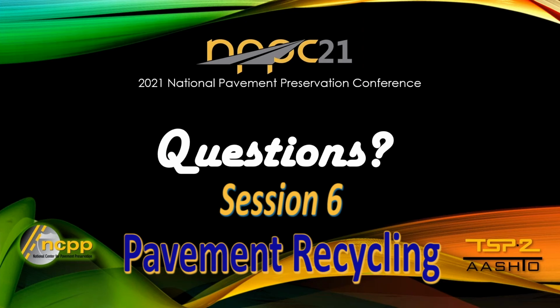It's heavy with binder. You've got some aggregate in there that you can reuse. And if it's an old, worn out chip seal, as typically we see on some of our urban highways that we're recycling, it does just fine. You can get in some problems if you've got 2 or 3 vintages of chip seals on top of the roadway you're trying to recycle. So we have milled that off before starting the recycling process, but if it's manageable and not a super thick chip seal or chip seals that are on top, those can be recycled in the hot in place process just fine.